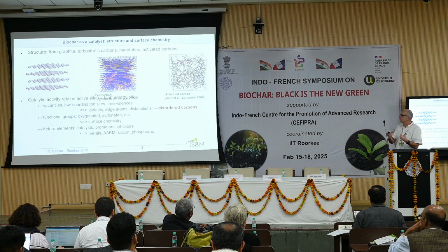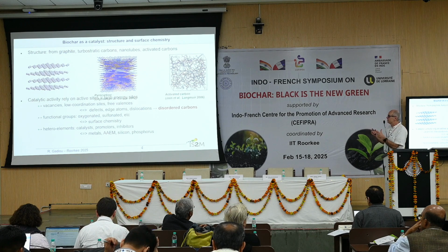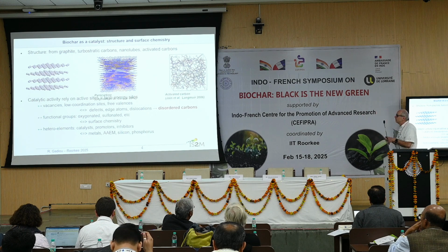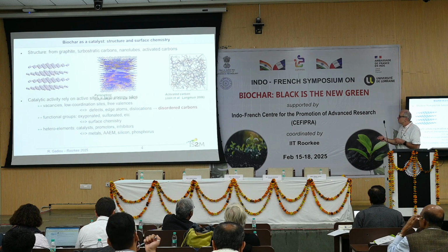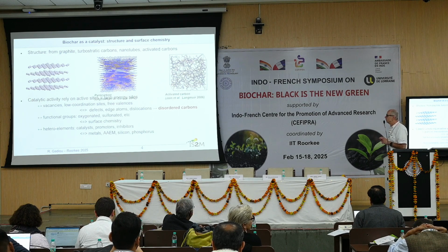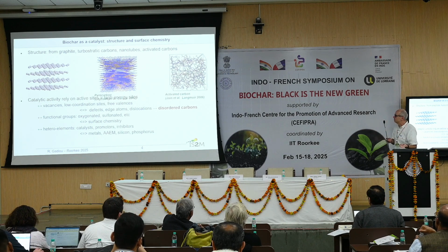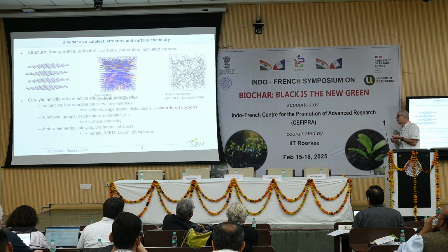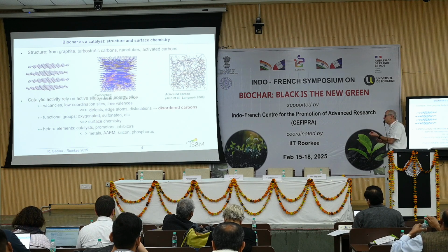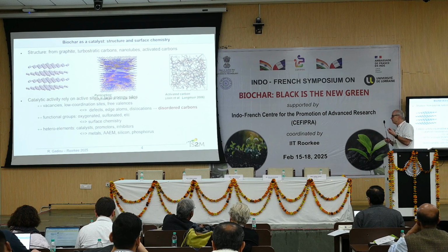Now, defects can be many different things. It can be, for example, what we call a Stone-Wales defect, which is just a small defect which will have no influence on the reactivity of the material. But some defects, like the edge or atoms which are lacking in a cycle, will lead to vacancies, low coordination sites, free valence, and all these defects, edge atoms, dislocations, and so on, are what we are looking for, because it is where we have activity.